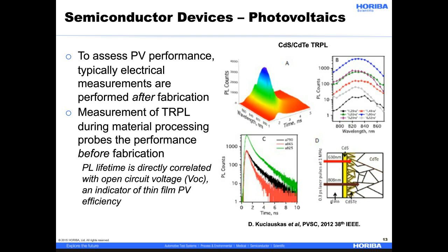In most TRPL experiments, lifetime measurements are carried out at a single PL wavelength, typically the peak wavelength. However, a spectrometer-based system was used here to map the temporal information across the entire PL emission curve. A 3D surface plot is shown, which maps out the PL signal as both a function of wavelength and time. By taking slices through this curve, one can look at either the spectral information at a particular time, or look at how the spectrum changes as a function of time.